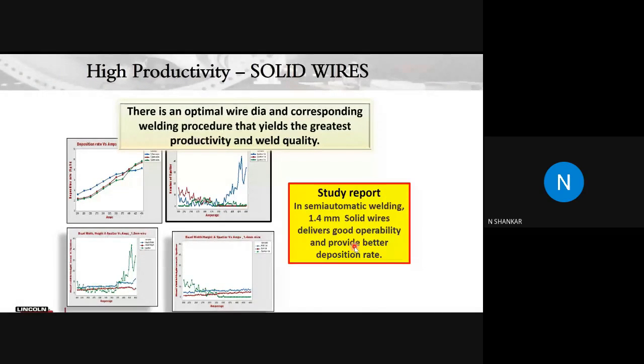So when the transition level comes where I could use a 1.6 mm wire, that was ruled out, because 1.6 mm was not able to give me the best result when I'm doing manual welding. In our robotic systems, yes, we have to again do the trials and decide. So we decided that when you're going to do manual welding, and also to some extent robotic welding, it's always better to use a 1.4 mm wire to give you the optimum deposition.